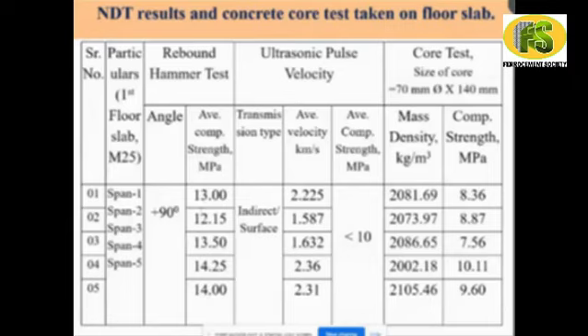And for every span, we have selected around 30 to 35 points where there is no steel reinforcement across the rebound. Then we found the ultrasonic pulse velocity. Here it is observed that the velocity is less because the concrete is undulated, the surface is not smooth. It is 2.225 or 1 point something like that. That means the compressive strength using the ultrasonic we get is less than 10 Newton per mm square.